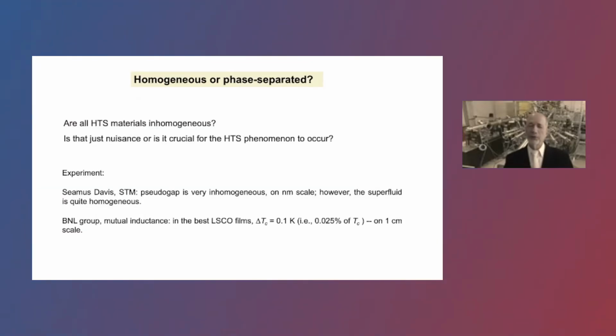Now, another point of controversy was, are cuprates homogeneous or inhomogeneous, phase separated? And certainly some of them are very inhomogeneous and can be phase separated. But the question is, is this necessary or is it just a complication? In other words, if you just want to explain the theory of the mechanism of high Tc theoretically, can we just work with a homogeneous one-band or two-band, three-band model, or do we need to build in the phase separation from the beginning? And experimentally, what was shown at this conference by Seamus Davis is that while the pseudogap is very inhomogeneous, it varies on a scale of a couple of nanometers, and it can vary by a factor of 2 or more. However, the superfluid density measured in the same sample with the same technique is actually quite homogeneous.